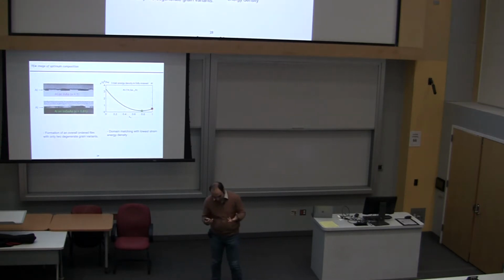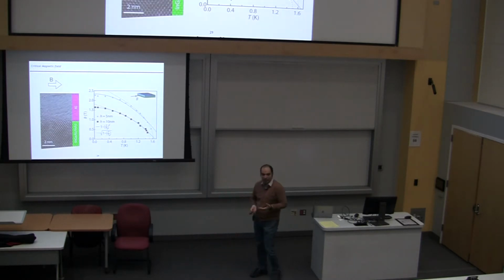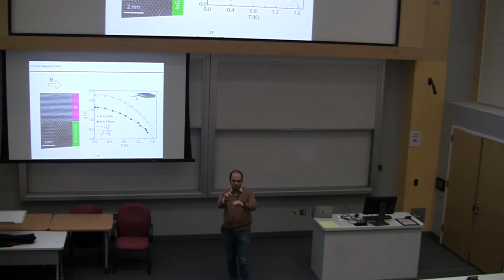So the power of MBE is that if we can grow material layer by layer, right, then you can choose to grow 2 monolayers, 20 monolayers, or 200 monolayers, right? So in this particular case, we obviously want to push the limit to grow a very thin film, because if you need a magnetic field, you know from the physics that the out-of-plane critical field of aluminum is always very low. But if you can grow a very thin film of aluminum, when you apply a magnetic field in the plane, you are in the paramagnetic limit of superconductivity. And there is this thing called the Clogston limit for the critical field that can actually kill that superconductor. And that is about 2.5 Tesla, 2.25 Tesla.